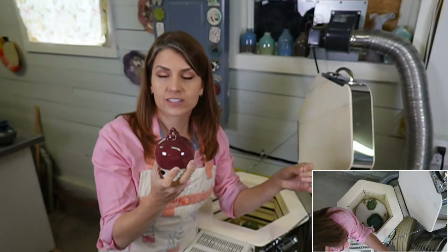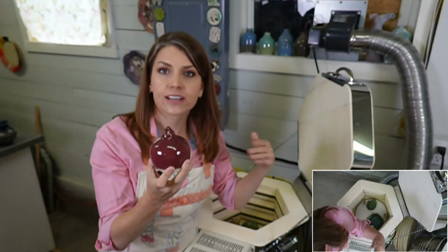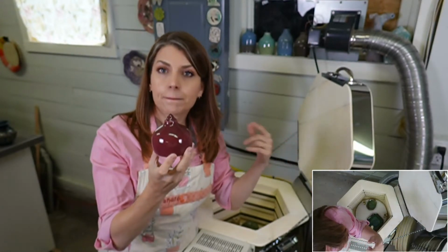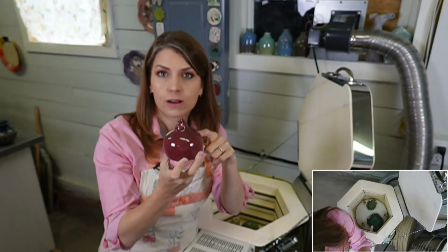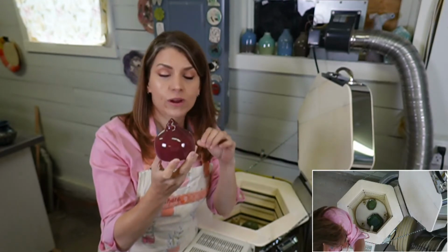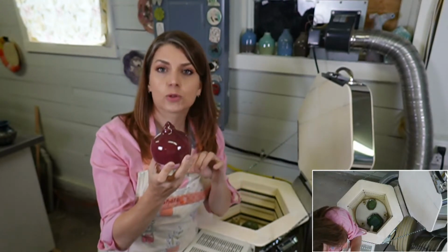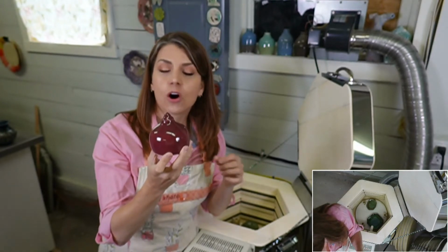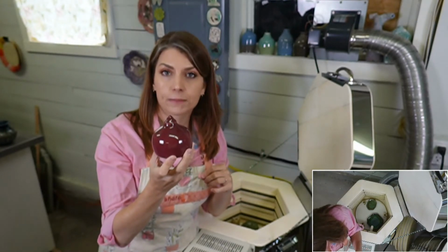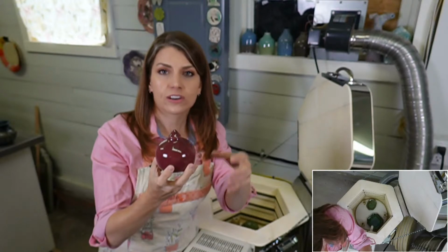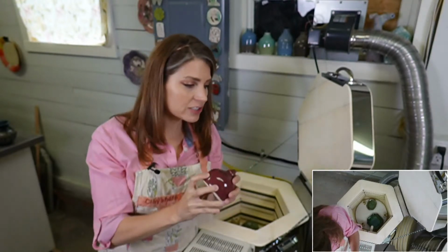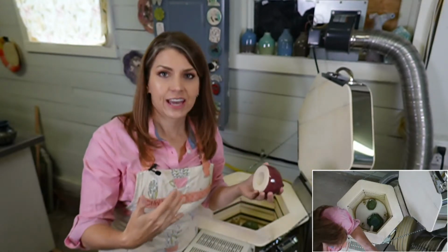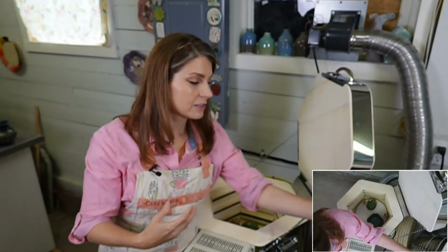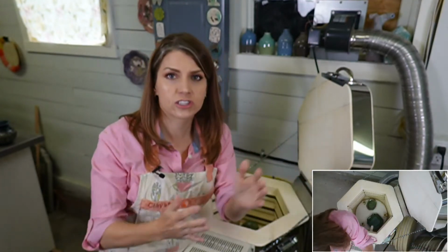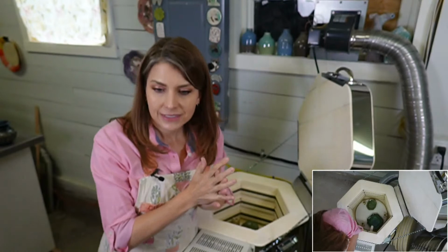The chemical water doesn't start coming off until we get later and it gets a little hotter in the kiln. But physical water comes off at the very beginning. So what the 1.5 hour preheat does is it takes it up to 180 degrees Fahrenheit, holds it there for an hour and a half for me, and that lets the rest of the water in the glaze come out. I just feel it's a better firing and you get better results for doing that. I've been doing that for years and years, and it's just part of my practice now.